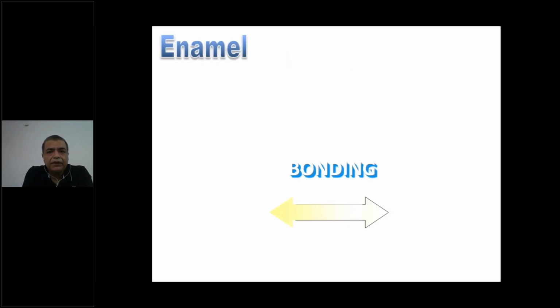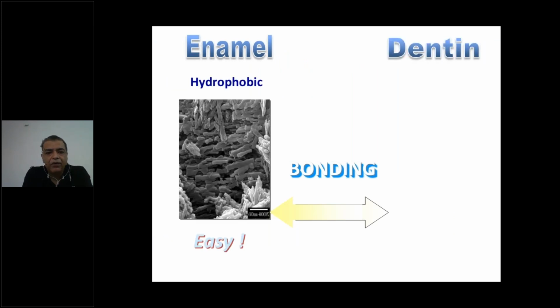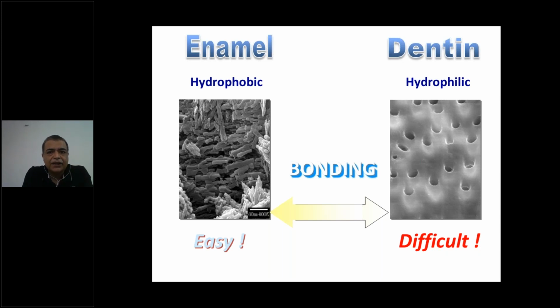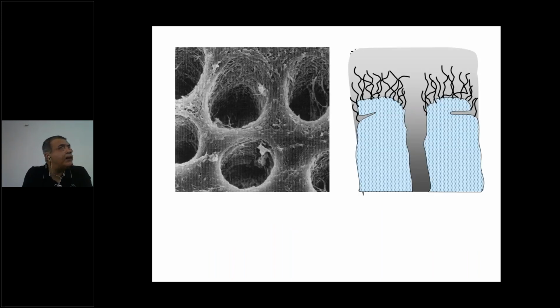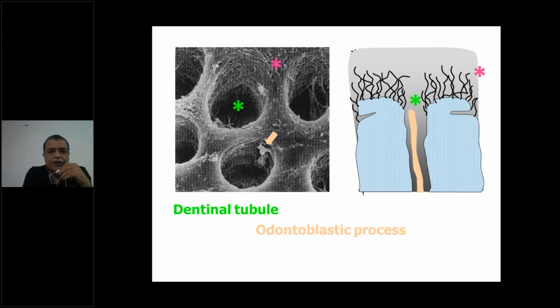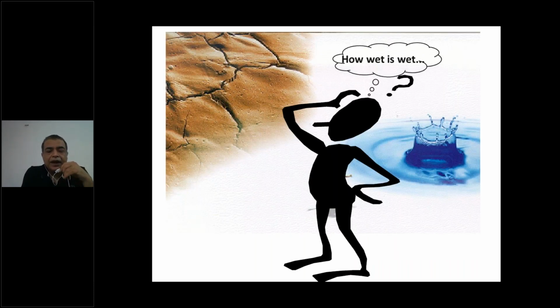So if you think about bonding with enamel and dentine, enamel bonding is very easy, because enamel is a hydrophobic structure, whereas dentine is a hydrophilic structure, and the bonding with dentine is much more difficult and much weaker compared to enamel. The reason is because you have multiple structures in dentine, like dentine tubules, the odontoblastic process, and intertubular dentine, and they all contain fluid. And this fluid makes it a hydrophilic structure, and that's why bonding is difficult with dentine compared to enamel.